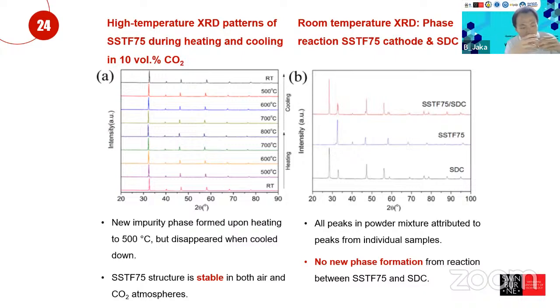and the anode, meaning that you operate the whole solid oxide fuel cell within one environment that contains the hydrogen, contains oxygen. So basically the solid oxide fuel cell will be exposed to reducing and oxidizing gases at the same time. And we can see that there are impurities that are formed when you are heating up to 500, but disappear when you cool down. And the essential finding in here is that SSTF 75 structure is stable in both air and CO2 atmospheres.